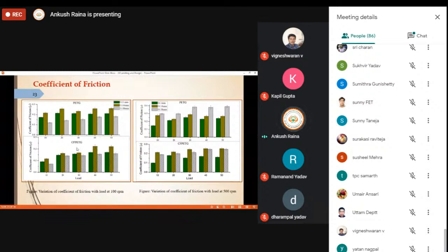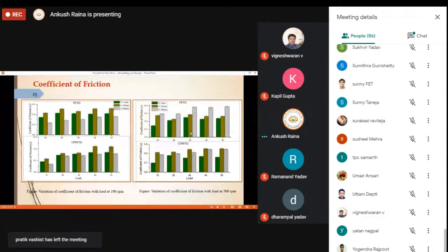Coefficient of friction over here is less in comparison to over here for both the reinforced and unreinforced PETG. So these results are basically due to the increase of adhesion at the high speeds. Basically, as I told you, adhesion is the binding of the two sliding surfaces with each other. So at high speed, there is a possible increase in the temperature, and due to the increase in temperature, the chances of adhesion are increased.